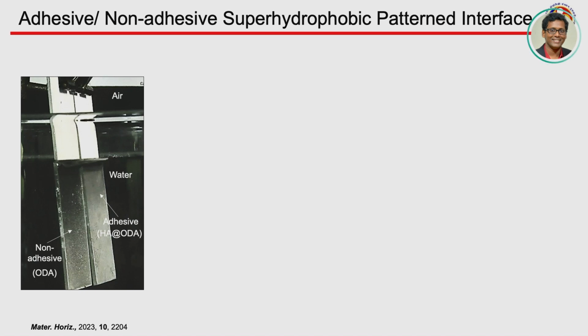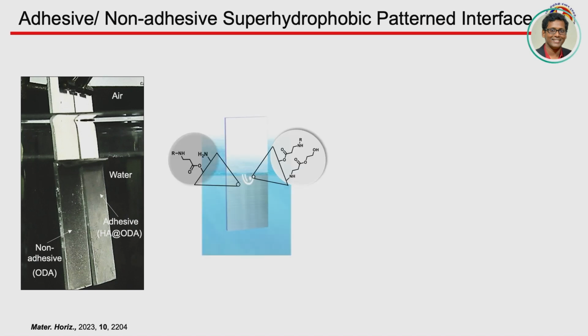It will be more when you have more trapped air, right? For non-adhesive interfaces you have more trapped air, more internal reflections, and it will appear more shiny, whereas for the adhesive one it's less shiny. Now, probably it is not very clear here, but you can see in the scheme, we can spatially and selectively modify whether it's a monofunctionalization or a difunctionalization. Depending on that, you can play with these adhesions.